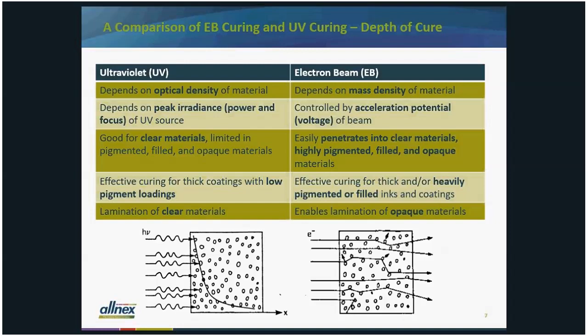UV depends on the peak irradiance, the power and the focus of the UV source, whereas with electron beam, this is controlled by the acceleration potential or voltage of the electron beam. UV is really good for clear materials and somewhat limited in pigment-filled or opaque materials. Doesn't mean they can't be cured, but depending on what those pigments or opaque materials are, it can be extremely challenging. Whereas electron beam easily penetrates into clear materials, highly pigmented, filled, and opaque materials.